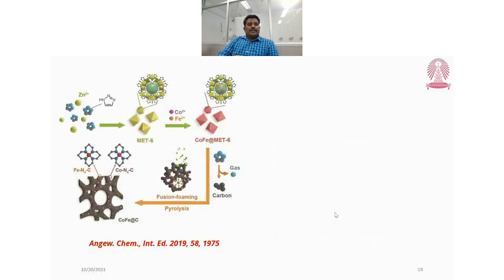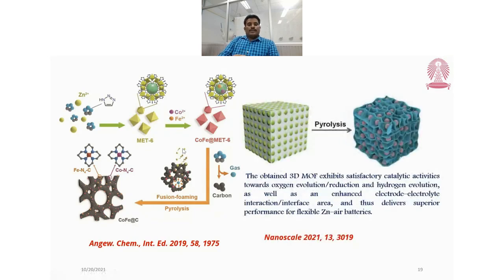Another synthesis method is a doping MOF. First, they prepare a single dimensional zinc and triazole MOF. This MOF is doped with cobalt and iron metals. Further, a carbon network MOF forms during pyrolysis. This is an energetic MOF. However, it has some difficulty in the synthesis method. The same research group synthesized a three-dimensional MOF, and they published it in a Nanoscale paper. This MOF can easily access the active sites during the OER and ORR processes, and it gives better performance towards a zinc battery.